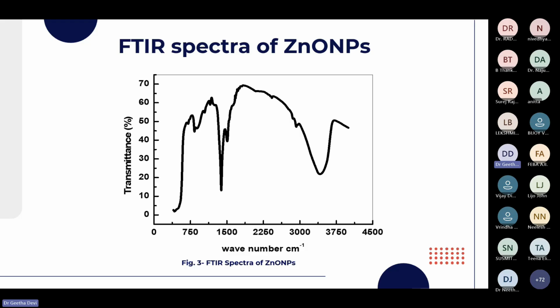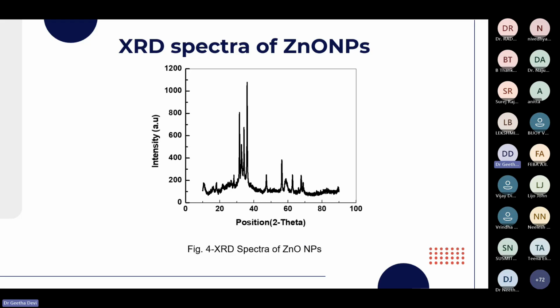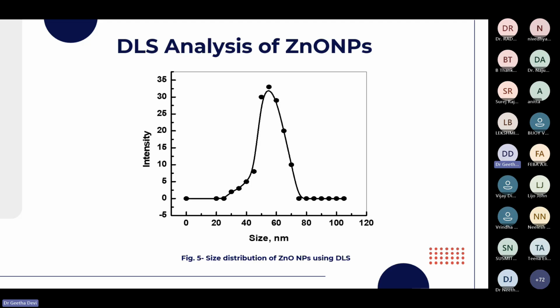This is the FTIR spectra of zinc oxide nanoparticles and XRD spectra of zinc oxide nanoparticles. This is the nanoparticle size. It is almost 40 to 65 or 70 nanometer, that is less than 100 nanometer only.